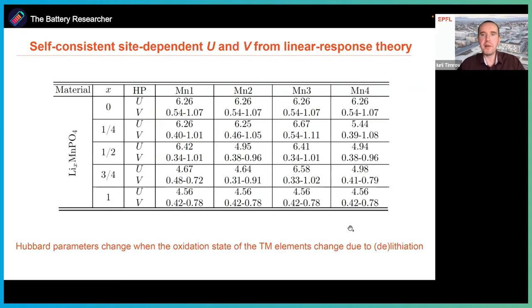This is the table where I summarize the Hubbard parameters that we computed using our methods for the case of manganese. We consider here five concentrations of lithium. And in these four columns, because we have four manganese in the cell, I report the values of the Hubbard parameters in electron volts. For example, we see that when we don't have lithium, so X equals zero, all four manganese have exactly the same value of the Hubbard parameter, which is 6.26, because all manganese are in the same oxidation state. But then when we fully lithiate the material, X equals one, the Hubbard parameter has changed, and now it is 4.56 for all manganese ions.